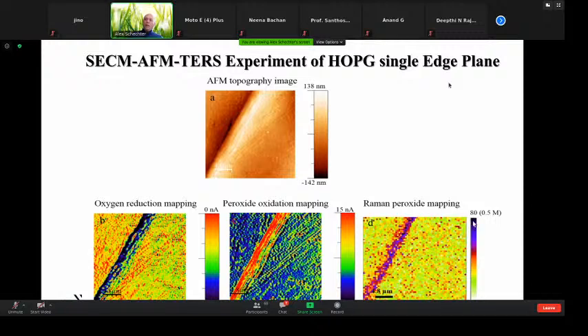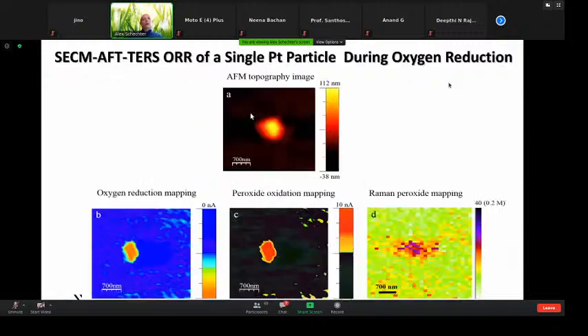So the purple means high concentration. Purple and dark is high, and yellowish and reddish are lower concentration. And when we compare the expected concentration from the electrochemical process, by using just Faraday's law, and compare it to the adsorption, we can see that we get the same concentration. That means that under the tip, we were able to measure 0.5 molar of peroxide. It's much more than you would expect in the solution, but under the tip, the concentration due to diffusion increases significantly. Then we again transpose that into platinum and measure again.